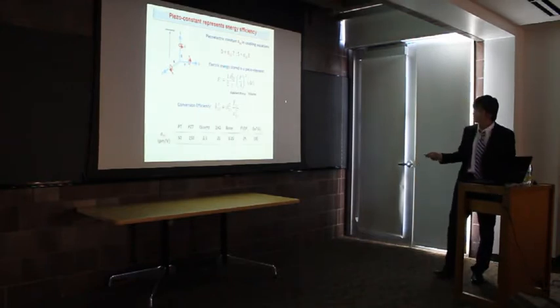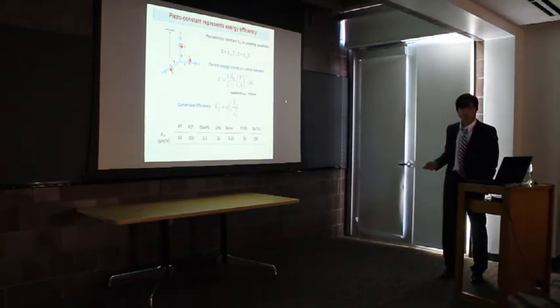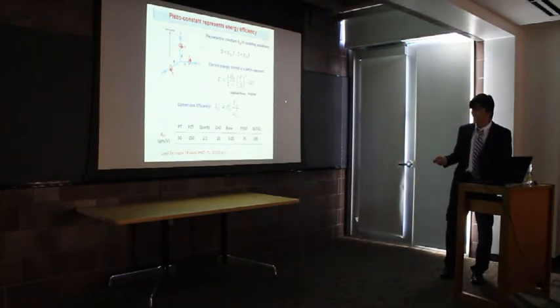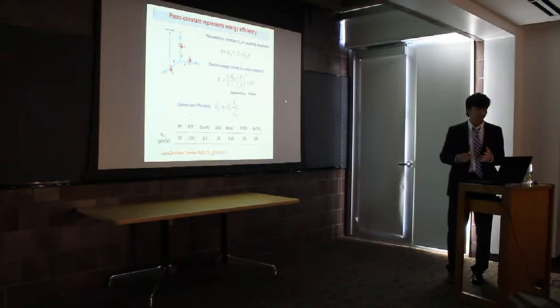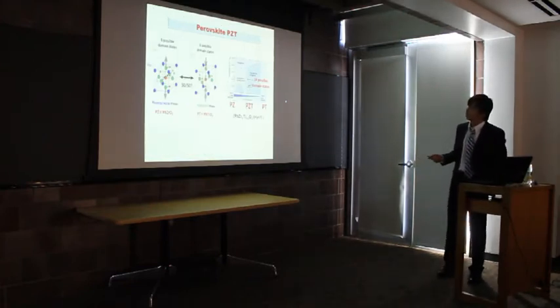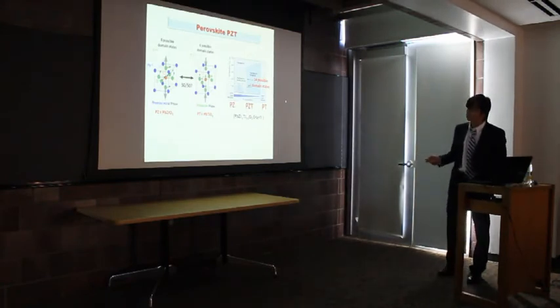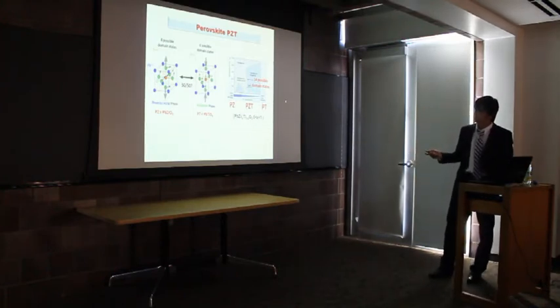If you're looking at common piezoelectric materials in bulk, it wouldn't be difficult to see that PZT, which stands for lead zirconate titanate, has the outstanding D33. So nanomaterials of PZT are really attractive, and people try to make them. One of the possible explanations for this enhancement of D33 is based on the crystal structure. PZT has a perovskite structure. Similar to PZT, less complicated composite materials like PZ and PT also have the same crystal structure.